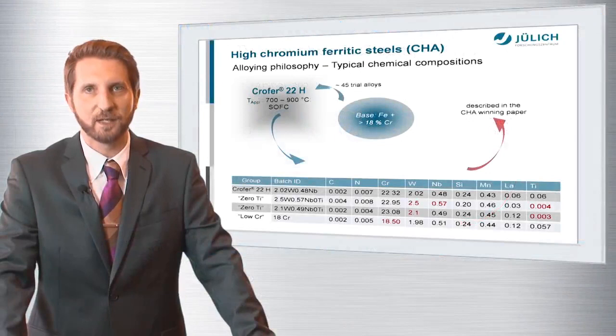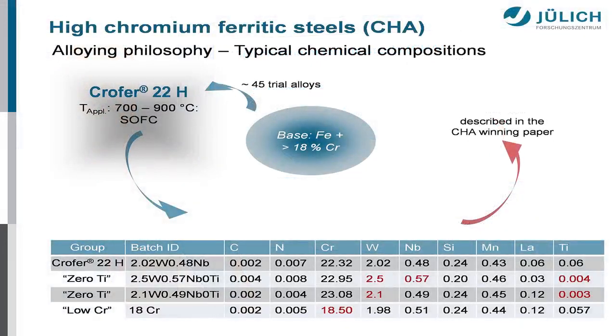And in the course of this alloy development, approximately 45 trial alloys have been produced. And some of these trial alloys featured fluctuations in chemical composition, like for example a lowered chromium content, like in the low chromium alloy, differences in tungsten content for the zero titanium alloys, like they are named right here on the slide, differences in niobium content, fluctuations in silicon content, and changes in titanium content. And the mechanical properties of these trial alloys showed very promising results, for example, for creep strength at lower temperatures in the range of 600 to 650 degrees C, and this is what we described in the award-winning paper.